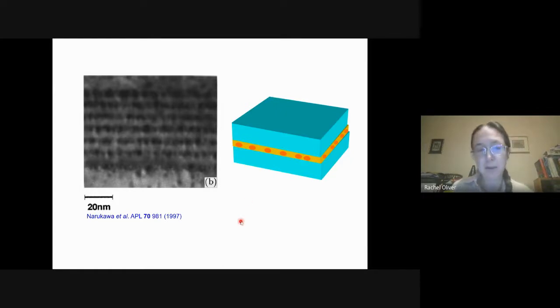And I think everyone was very excited and very satisfied that they'd understood what was going on with these LEDs, that the high indium content regions were protecting them, preventing carriers from diffusing to dislocations. And this really was seen as the answer to the problem. And there were patents about how you would optimize these high indium content regions, which was people improving the processing of these devices to try and improve the performance.